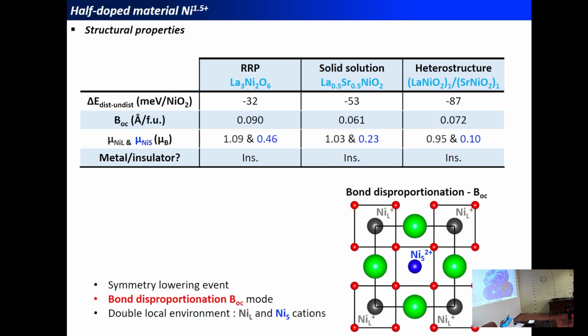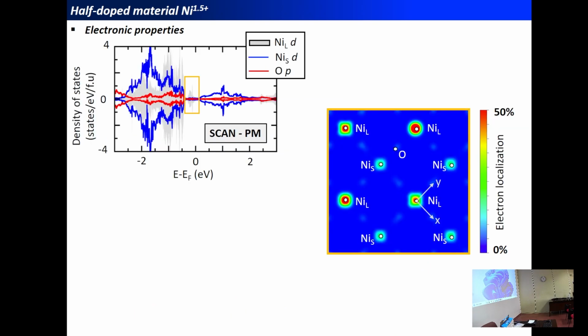And so we expect to have a charge ordering between nickel 1+ cation and nickel 2+ cation, because in the half-doped system we are in the nickel 1.5+ formal oxidation state. Effectively, if we look at the density of states, we can confirm that between the large nickel cation and the small nickel cation around the Fermi level, we have an asymmetry appearing in the density of states. Below the Fermi level is dominated by the large nickel cation states, while the small nickel d states are above the Fermi level.